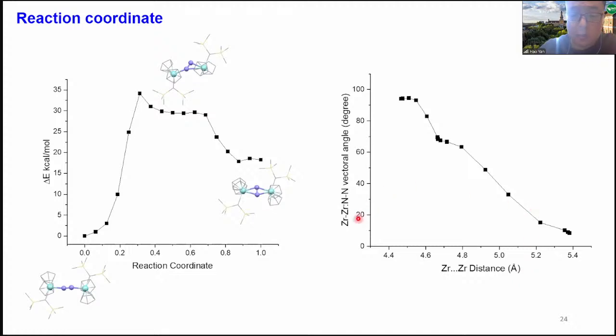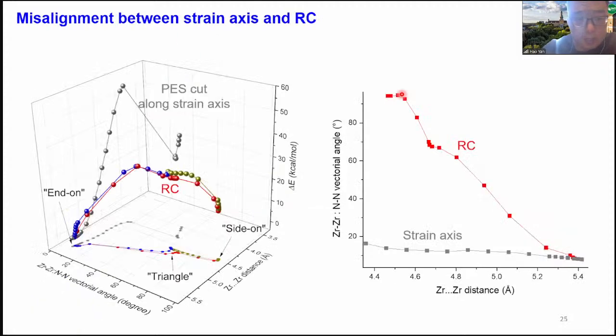But there's also the rotation of the nitrogen species relative to the zirconium, which we capture here by the zirconium-nitrogen vectorial angles. So it goes from almost 0 degrees at the beginning to close to 100 degrees at the end. So you need two motions in the molecule for this reaction to happen.